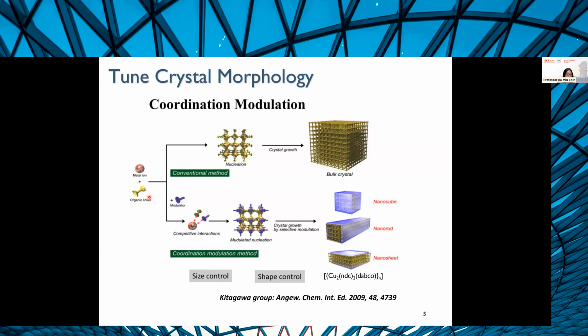But you also can throw in a modulator, and when you do that, this modulator, which has the same functional group as the organic linker, but only has one group instead of two, so it can't extend the material into a framework, will compete with the organic linker. And so you have these interactions that modulate how fast these crystals nucleate. And you also have selective interactions, which then lead to different types of crystal shapes as well.